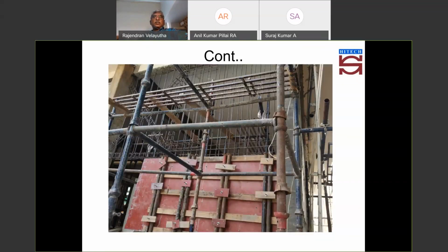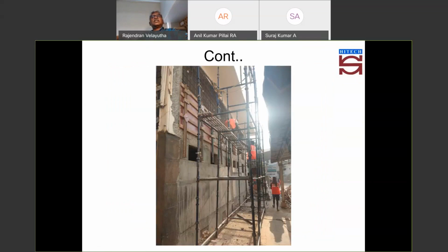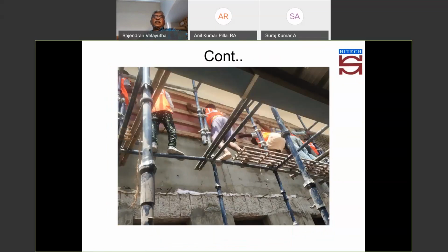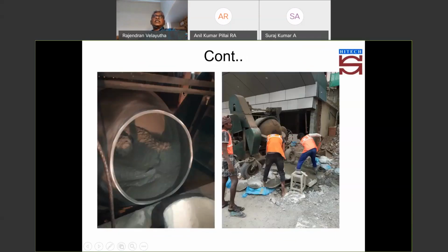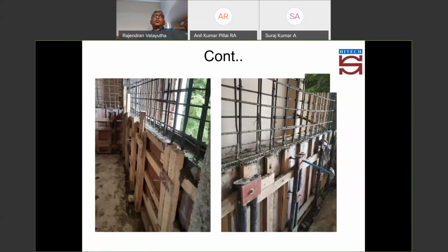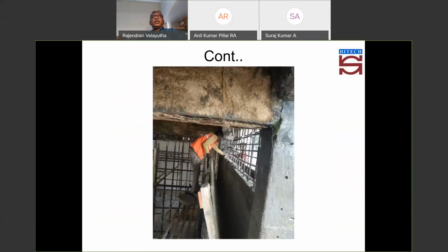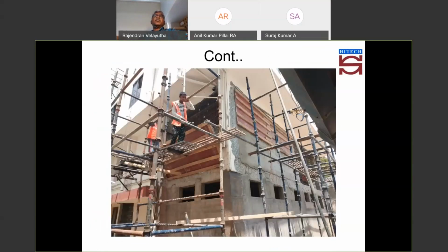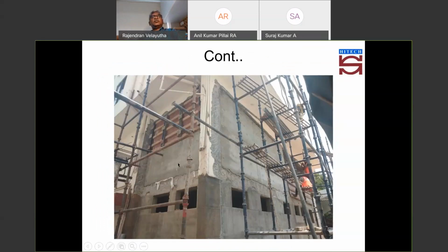So the formwork has been done, the first layer, and then the second stage of concrete is done. It has been taken up to the top, and then you just break open and pack it into the existing beam, and then start pouring this SCC, and you have absolutely no problem as far as the contact between the soffit and the beam is concerned. I'll just show you. This is how you will have the contact between the existing beam and this. There's no crash, nothing.